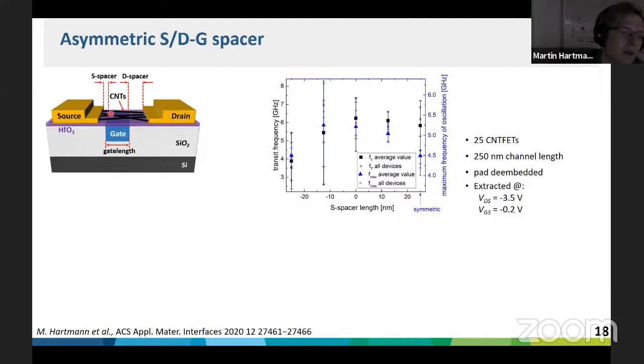And then we went one step further. We thought, okay, the main important barrier is the barrier between the source electrode and the CNTs. So when we now shift asymmetrically our gate electrodes towards the source, we get an enhanced control of the source barrier, but we reduce the parasitic capacitance towards the drain electrode. So we made asymmetric devices and we studied them. And what we found here was that the highest transit frequency and maximum frequency of oscillation were achieved for around 0 nanometer source spacer.